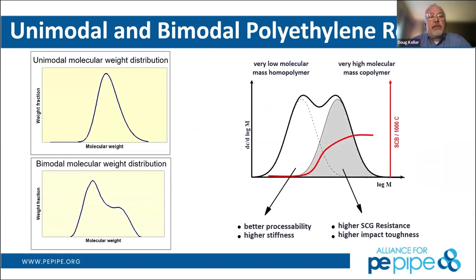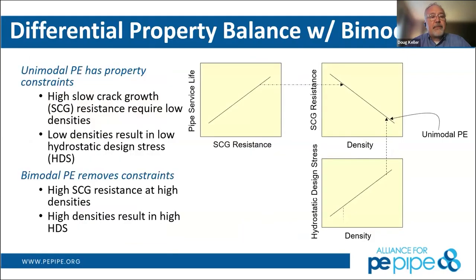When we talk about polyethylene, there's two different types of polyethylene for pressure pipe application. One is unimodal, the other is bimodal. Most of the polyethylene PE 4710 materials today are bimodal polyethylene, which means that we can tailor the material to meet particular needs. One of the issues in the past with polyethylene pipe has been slow crack growth resistance. Slow crack growth is the common failure mode of polyethylene pipe in the absence of third-party damage. What we've been able to do is take that co-monomer that I talked about and put it into the high molecular weight region of the polyethylene using the bimodal process. That allows us to get superior slow crack growth resistance, so that we've now pushed out failure by slow crack growth well into the future, probably well beyond the design life of the polyethylene pressure pipe system. Next slide.